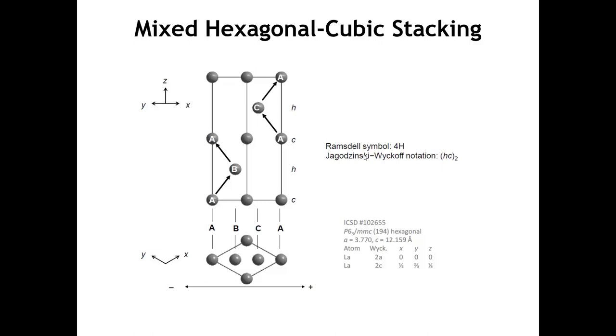Now, let's talk about a few structures of metals that don't quite correspond to one of those four structures we've talked about already. Just as the cubic and the hexagonal close-packing have equal packing efficiencies, we could have structures which have other stacking arrangements that are not ABABAB or ABCABCABC. You could have something like shown here for lanthanum where you have ABACABAC. That's also a close-packed arrangement, but it's a different pattern than the two simple arrangements we've talked about so far.